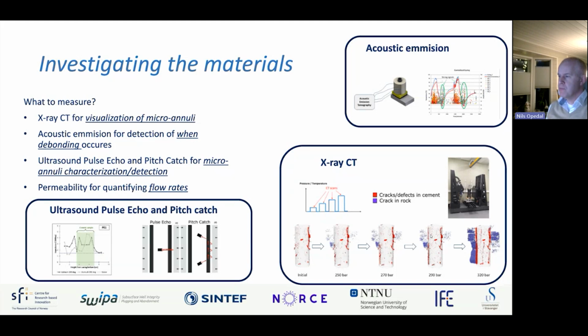So we have access to a CT. Before we had a medical CT, now we have our own industrial micro CT. It's a small photograph, but in the bottom right photograph, you see one of our cells located inside the CT, enabling us to scan specimens under pressure. The collage of photographs is just trying to show what it can look like for some of our specimens when we go from the initial phase and have subsequently higher inner casing pressures. You can see that the cracks and defects in cement and all the cracks in rock are forming and growing as you have larger inner casing pressures until we have full catastrophic failure at 320 bars differential pressure.